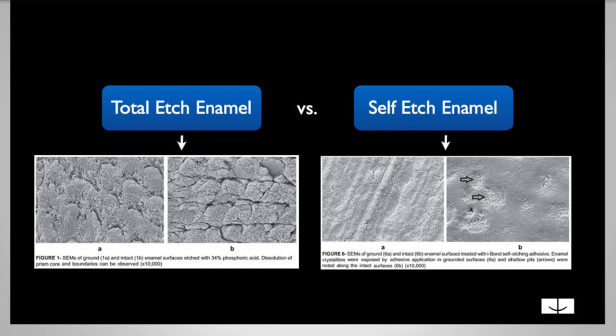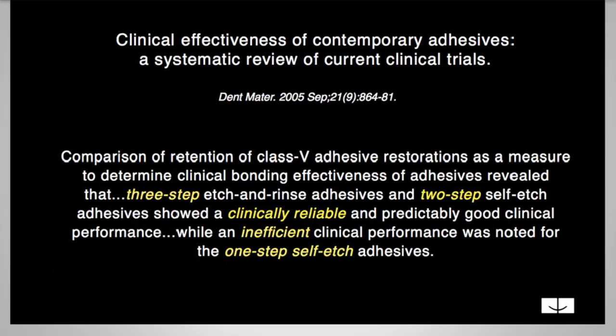Here was an interesting article that was done in 2005. It talked about 3-step etch and rinse, 2-step self-etch. Both of those are clinically reliable. But the 1-step self-etch adhesives they found was inefficient for clinical performance. So be very careful and very judicious on when you're using a 1-step self-etch system.